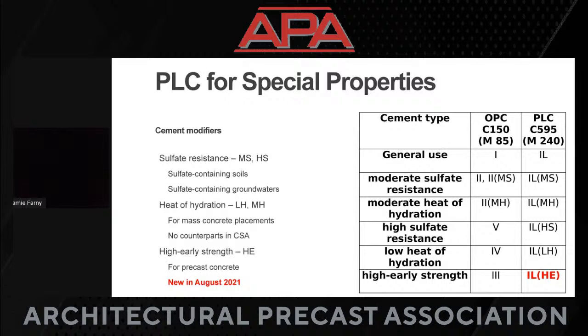So I just talked about sulfate resistance a little bit. Depending on your cement supplier, you may have an option to specify a special type of cement. For instance, for sulfate resistance, we can append an MS or an HS designation to our type 1L. So where we have a type 1, we just put in a type 1L. If we have a moderate sulfate resistance type 2 material that we typically use, talk to your cement supplier. They may supply a type 1L MS. This material would be tested to demonstrate that it can resist sulfate expansion under exposure to sulfates, and it has to be tested in order to receive this MS designation. Similarly, if you use a type 5, you might have a high sulfate resistant type 1L available to you.